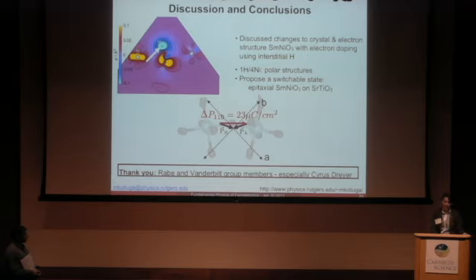So we looked in the 4-nickel unit cell, we looked at a whole bunch of different types of magnetic orderings. In terms of the electron doping and the overall qualitative changing of the band structure, there's no difference. Once you get to fully doped structure, you see the same behavior, and when they do magnetic measurements of the fully doped structure, there is no long-range magnetic order. So in that case, we decided not to focus a lot on the magnetic order.